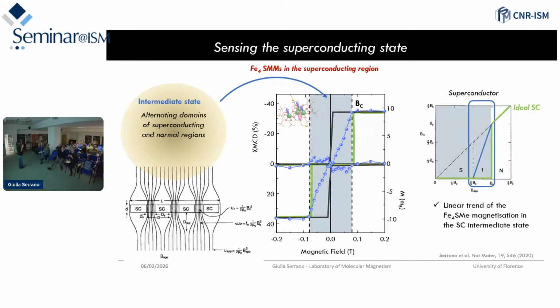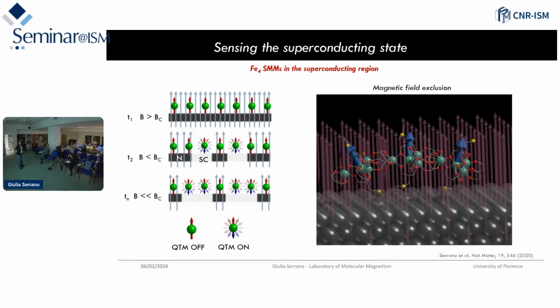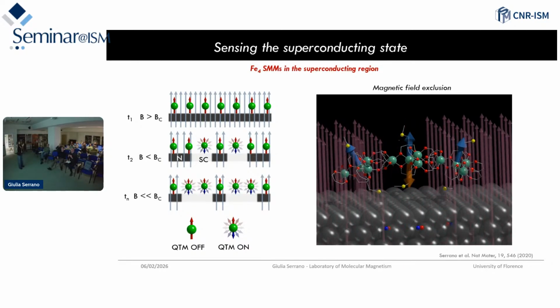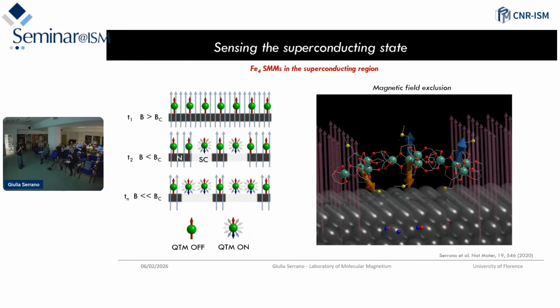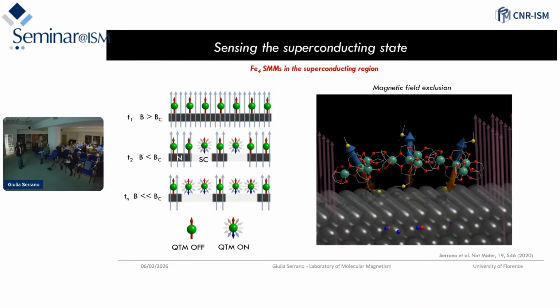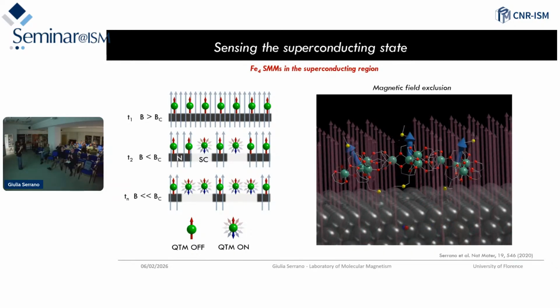So this Meissner state doesn't exclude the field suddenly at once, but depending on the geometry of the superconductor, it does it by forming alternating superconducting and normal domains. The superconducting domains, in which the field locally is zero, then enlarge and expand linearly by decreasing the field. So we have a linear increase of these superconducting domains, and basically what is going to happen is that we linearly increase the fraction of molecules performing quantum tunneling of the magnetization. We also performed some simulation on that. This explains this linear decrease of the magnetization that we observed between the critical field and zero.